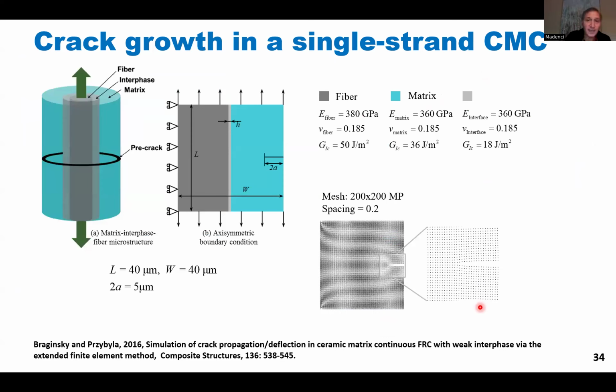Then, let's say you have a problem where you have a discontinuity, right? Here you have this single strand ceramic matrix composite. So this is the matrix, this is the fiber, and this is the interface. In ceramic matrix composites, the idea is the load is carried by the fiber. So if a crack initiates, they want to deflect the crack growth. They design the interface in such a way that when the crack reaches the interface, it propagates along it. In other words, it's not going to go through the fiber because the fiber carries the load, okay? So that's the idea here.